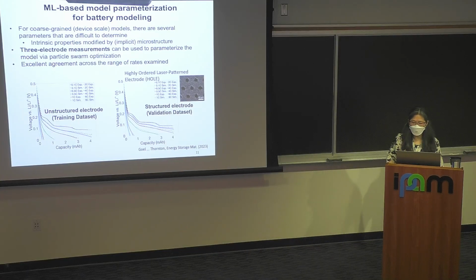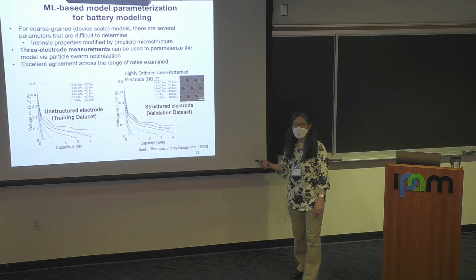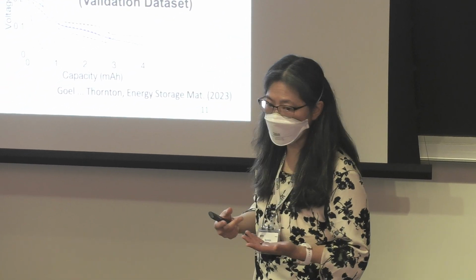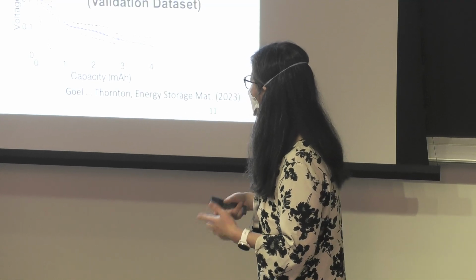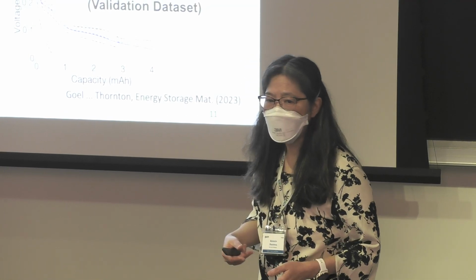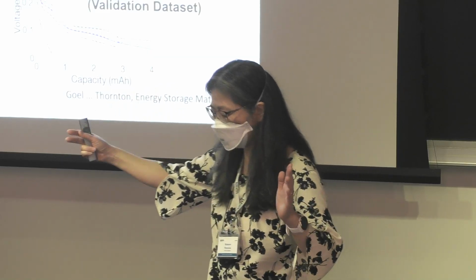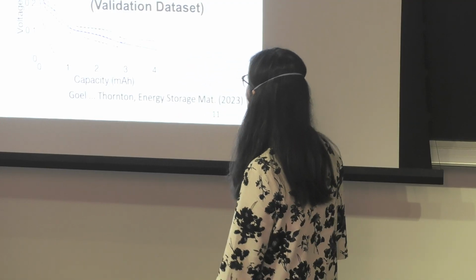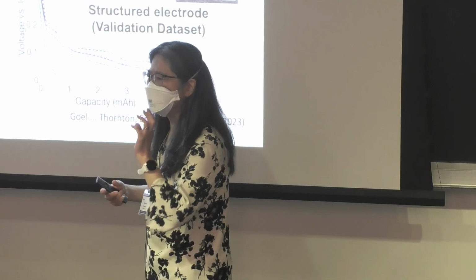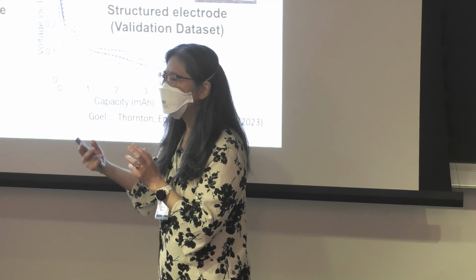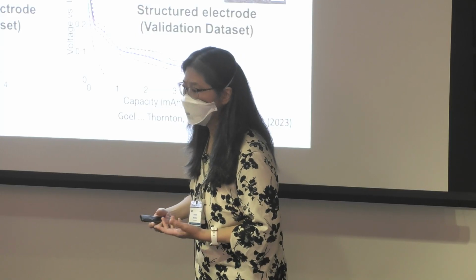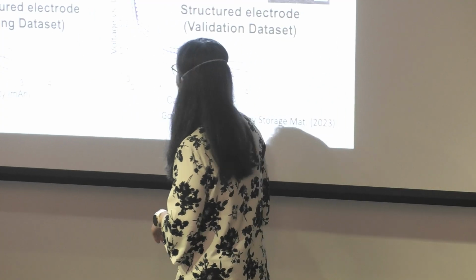And for the electrochemical problem, we try to narrow down as many parameters as possible from experiments and simulation input. But when we try to simulate the whole cell, we coarse grain. I'll show you some of the equations later on. Those are transport properties that are also modified by the microstructure, so you can't just measure them. In those cases, we also have to do some parameter optimization.